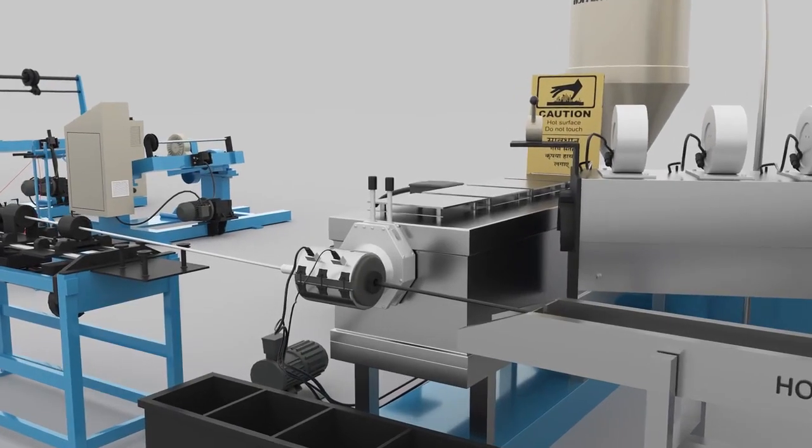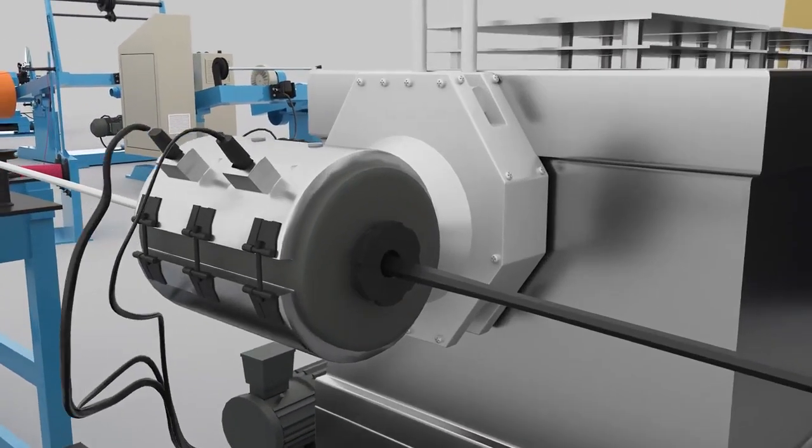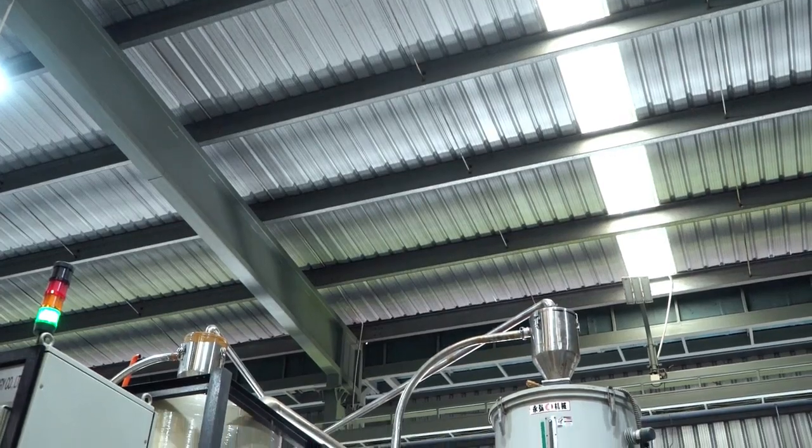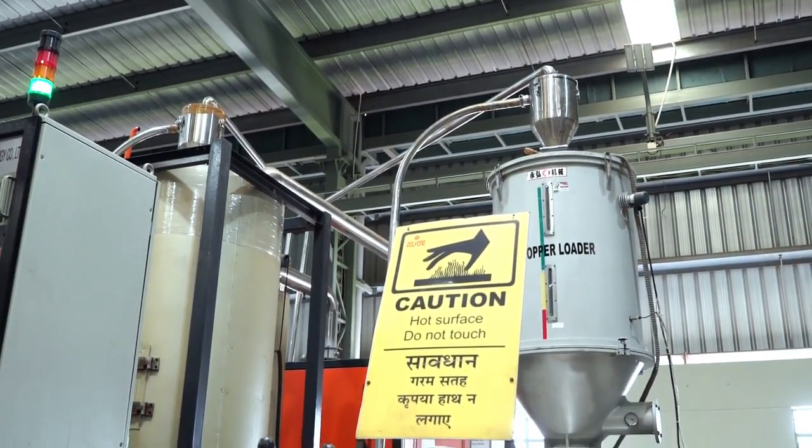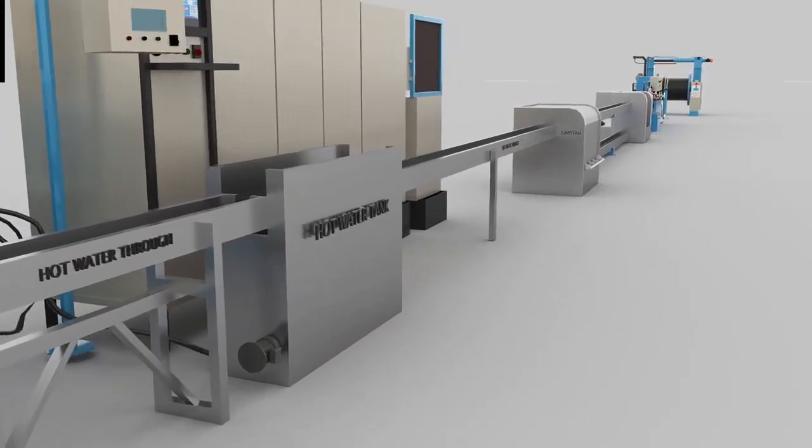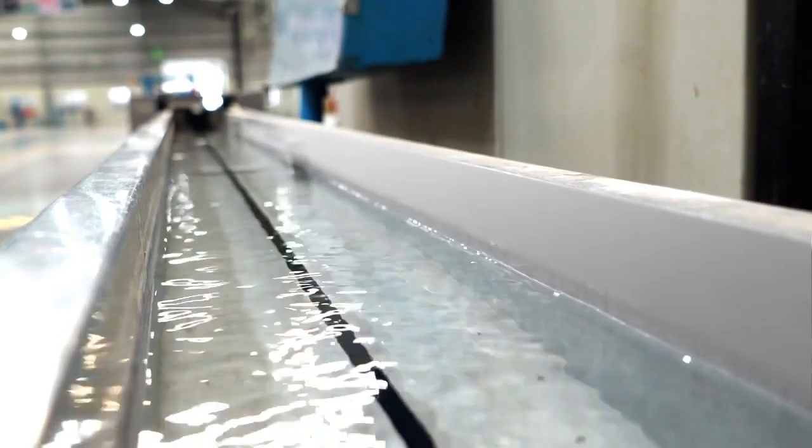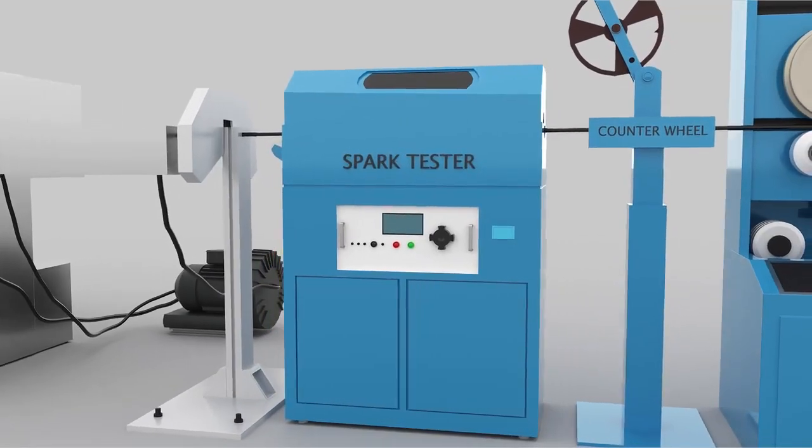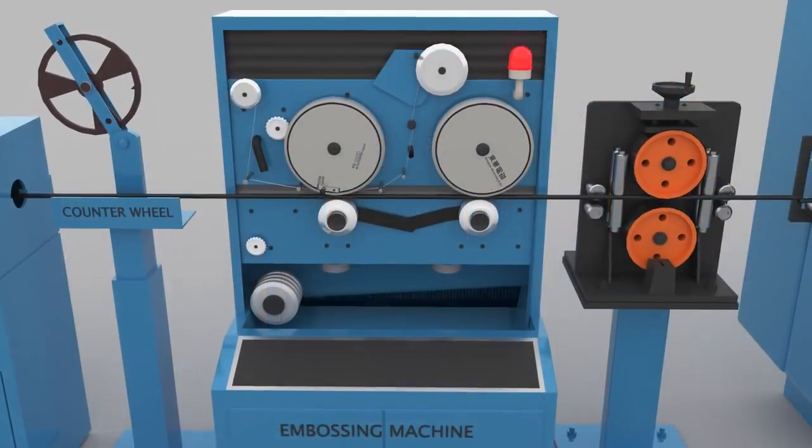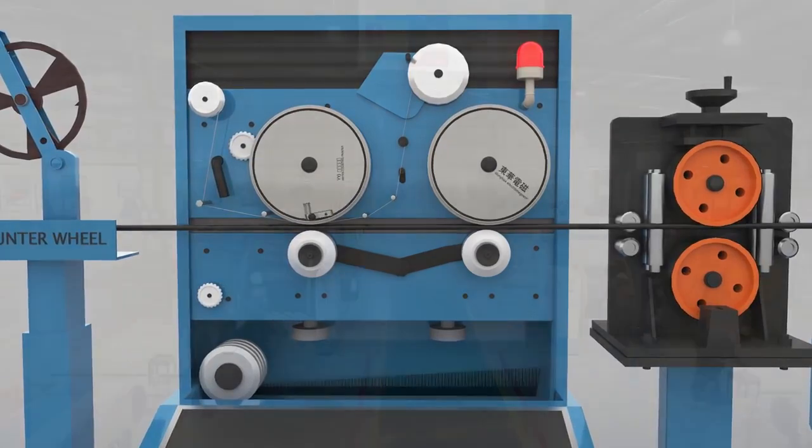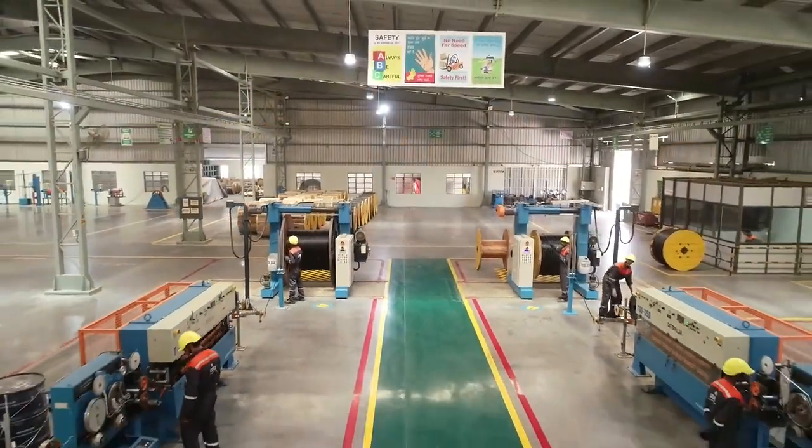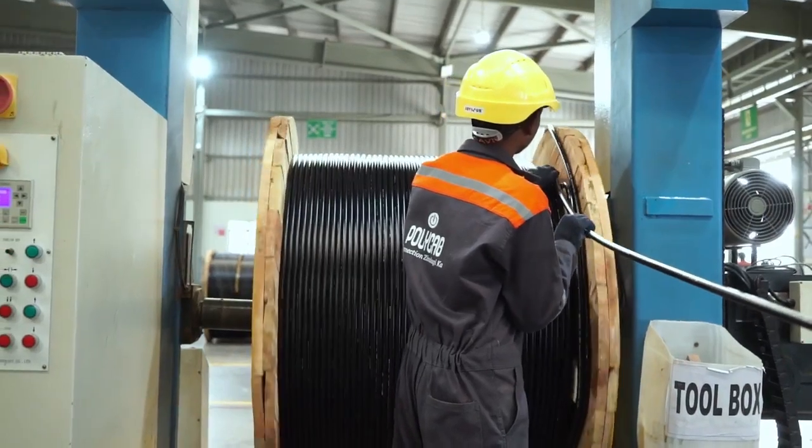The cable passes through extruder unit where compounds such as high density polyethylene, low smoke zero halogen, nylon PA12 to name a few, provides outer jacket to the cable. After extrusion, the cable runs through hot and cold water and dries off. Spark tester, in case of armored cable, checks for any foreign particles. The technical information of the cable are either embossed or printed over the cable. The cable is then bound up on wooden spool.